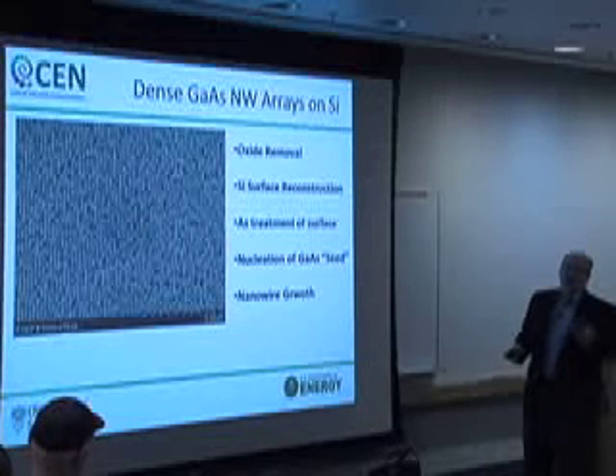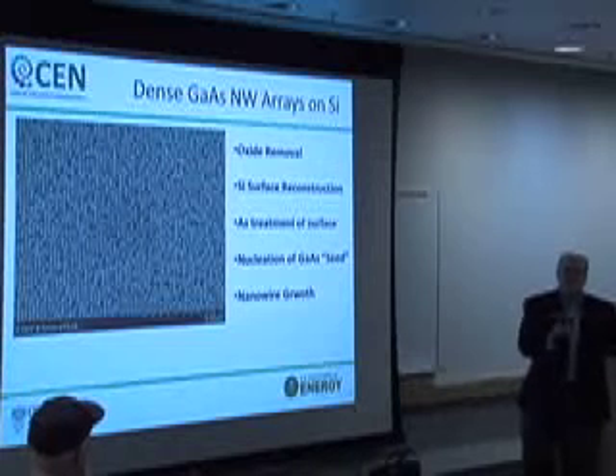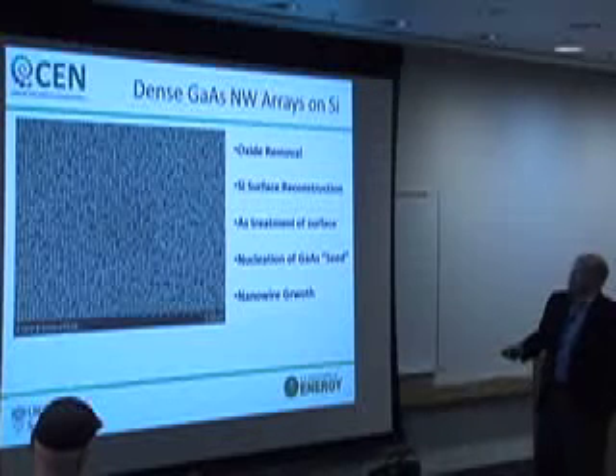Anyway, so we've applied this to the growth on silicon, and growing on silicon is tricky because there's a native oxide naturally on silicon, and because of the polar-nonpolar interface between silicon and gallium arsenide, getting the right ordering of the crystal on the surface is a challenge. But we've developed techniques based on a lot of literature from the 80s and 90s where people did a lot of this work, so that we can control the surface. It's treated with arsenic. It's either got two-layer steps. Well, these are 111 surfaces. That doesn't apply, but they're treated with arsenic, so it's an arsenic-rich surface. And we grow ordered nanowires on the silicon surface. This shows a magnified image of one of those.